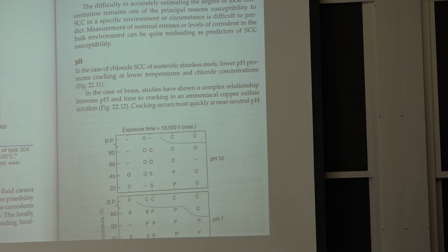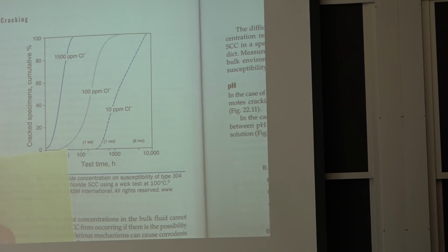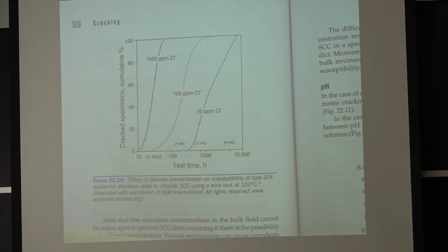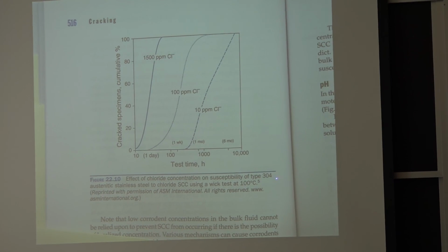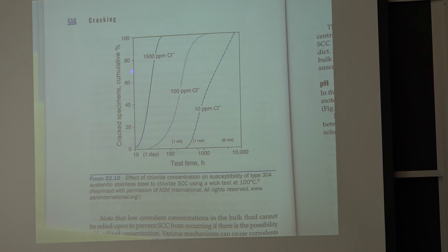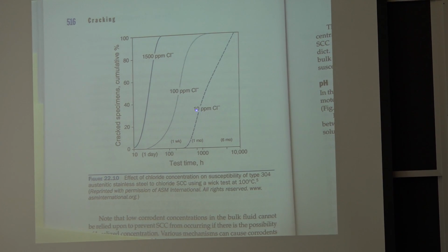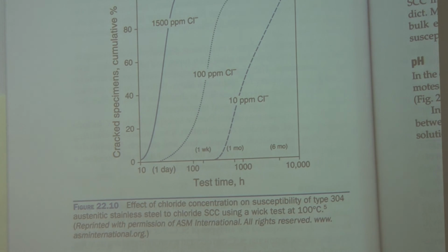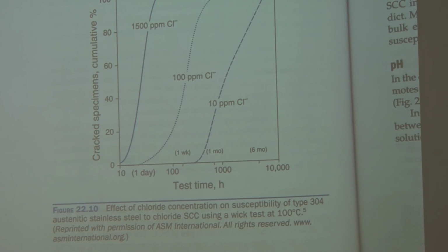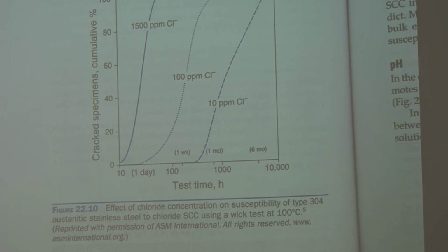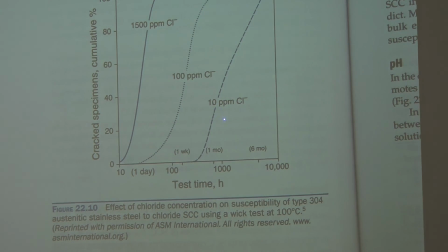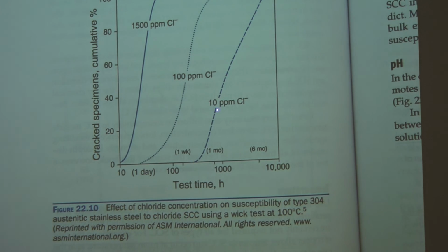Here's another thing that talks about effect of chloride concentration on susceptibility of type 304. Test time in hours versus the cracked specimen cumulative. So I got a bunch of specimens, and you can see as you march up from 10 ppm chloride. If you condense the air in Cambridge, Massachusetts, because I've done it, and measure the chloride, it's 5 ppm chloride. The drinking water, which is pretty good in this area, except in the winter when they're putting salt on the roads, is around 10 or 20 parts per million chloride.